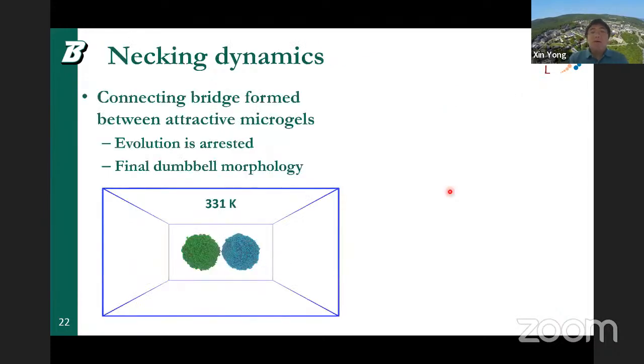And so we further looked at the detailed dynamics of the necking because we found this very interesting. As this microgel, which is considered to be more like a solid particle, although deformable, demonstrates traits of a liquid droplet, we looked at the dynamics more carefully. So here we put the microgels very close to each other, and we don't apply any strain, because we want them to interact naturally. We observe that the neck forms between these attractive microgels in the collapsed state. However, the evolution is highly arrested, and at the end of the day, we get a dumbbell morphology.